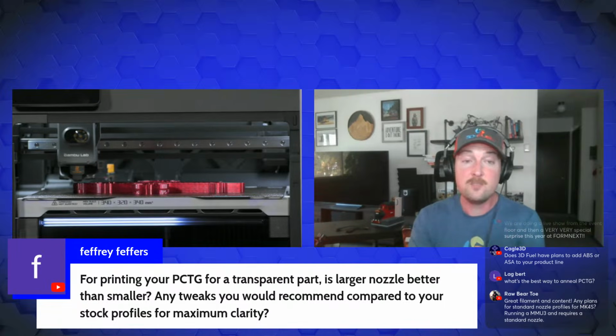You've got to be aware of that, because it is possible to print too slow, and it's possible to print too hot. Then the other challenge I had was getting the top surface layers to be perfectly smooth, so that it would be more optically clear from more directions. When the extrusion is going in the same direction, it's a lot easier. But even if your top layers all go in the same direction, by the time you get to the very top, getting it so that you don't have a tiny visible ridge or depression between the extrusion widths is challenging. So you really have to sit there and tweak the extrusion flow rate, the flow rate multiplier, to get it dialed in. And like I said, I couldn't quite get it across the finish line before other projects piled up.